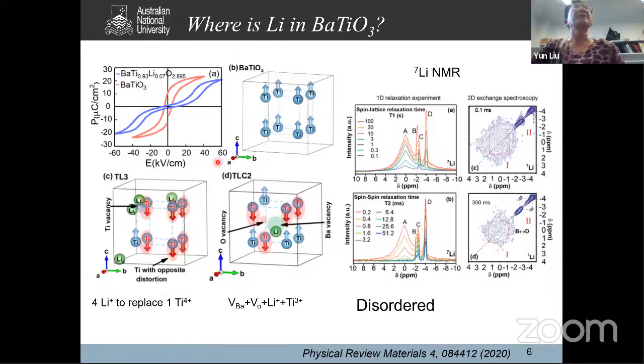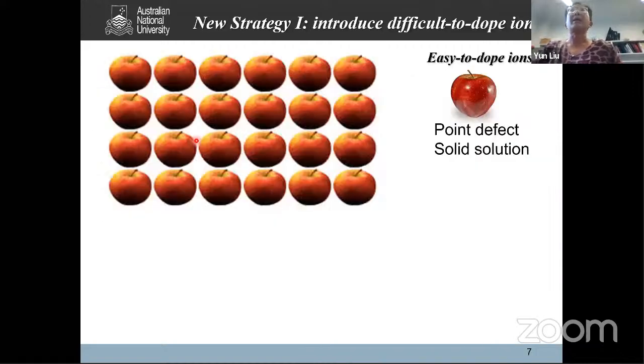Okay. So from that we can actually divide the doping ions into 2 types. One is easy-to-dope ions. In that case, they are similar in size, similar in electronegativities, so you introduce them into the material. It doesn't have a big impact on the surrounding chemical environment. They may move around a little bit, but it doesn't change much. So in that case, they just occupy that site, replace the atoms, and form point defects or make a solid solution. This extrinsic ion doping or ion substitution does change the property, but you will never create a new function. So they have a quantitative change, but not a qualitative change.